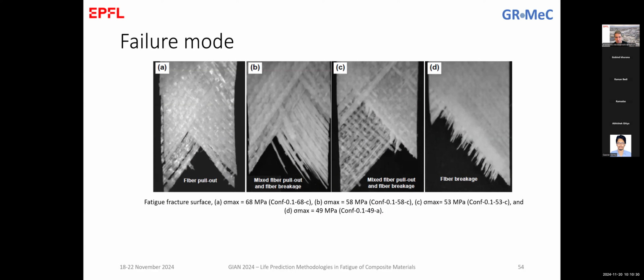Coming back to the discussion that we had before and trying to explain this effect, we can say that at the high stress levels we have this fiber pull-out because, if you can imagine, the excessive load was significant and pulled out the fibers directly. You remember here, we have the specimen in the machine loaded here, and the fibers are like that. So they are not continuous fibers from one loading point to the other. So at high loads, these fibers were torn out directly from the specimen with very local, very little damage in the bulk of the specimen.